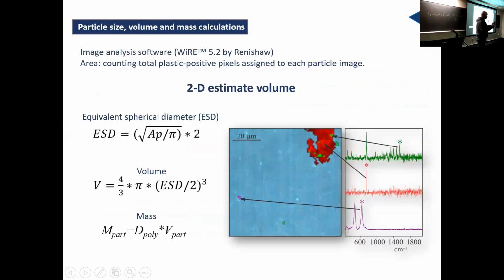So now I have particles. I can calculate the area of each of those particles, and then I can calculate the equivalent spherical diameter, which is a diameter, assuming that that particle is a sphere, and it gives me a value. And with this diameter, I can calculate the volume of these particles. This comes with a lot of assumptions and a lot of uncertainties, but we take into account all those uncertainties in every step of our methodology, our protocol.